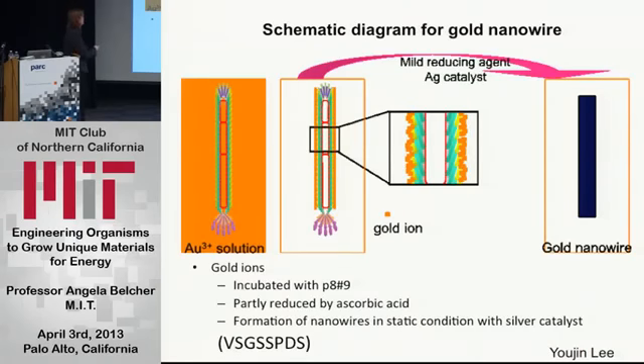But basically, through the selection process, here's one particular kind of sequence that we've panned and found that was really good for growing gold. And so you start with gold plus 3. You have your particular virus that you pulled out through your selection. You have a mild reducing agent, and you can make gold nanowires. And so you say, well, that's probably not so surprising. But we make these nanowires with 98% conversion efficiency from gold ions in solution into gold wires.